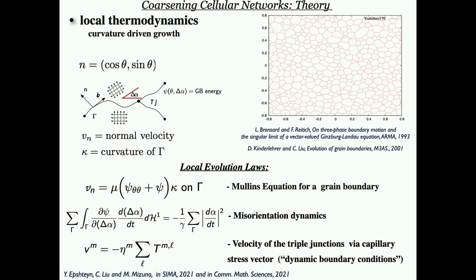And what we see here is polycrystalline samples, so with two-dimensional cells that represent grains. Here is a zoom view on three grain boundaries that meet at what we call a triple junction. So in our model for now, we assume that only triple junctions are energetically favorable. It's not a bad assumption. Of course, it does happen that more than three grain boundaries could meet, but it's a more rare event.